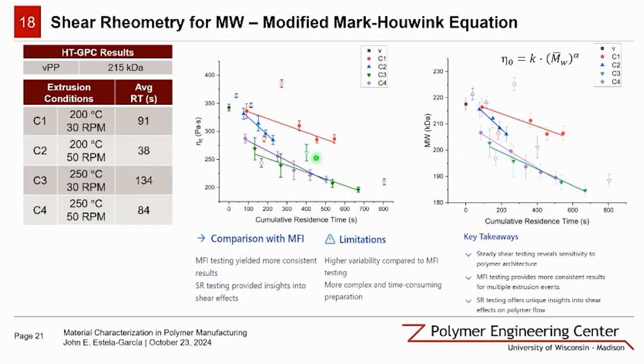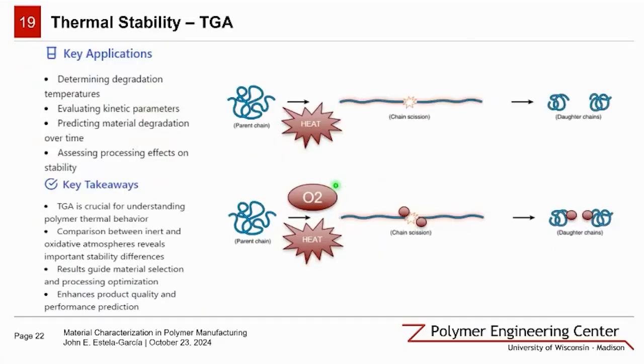Rheometry was very useful in constructing viscosity curves that allow us to compare the entire flow behavior and contrast it against recycled materials to determine if we can match the same flow qualities. This allows us to minimize process parameter changes required to process recycled feedstock. Results can also be used to quickly determine if the material is suitable for specific processes.